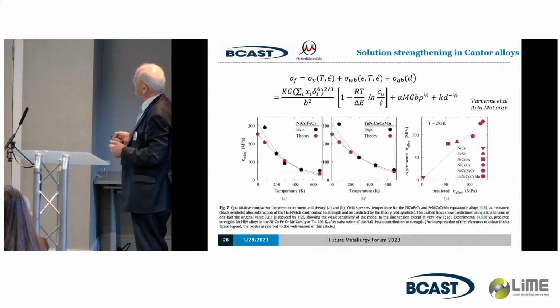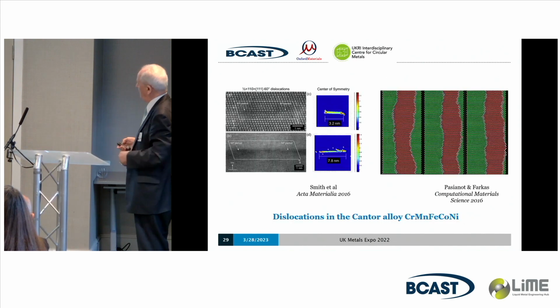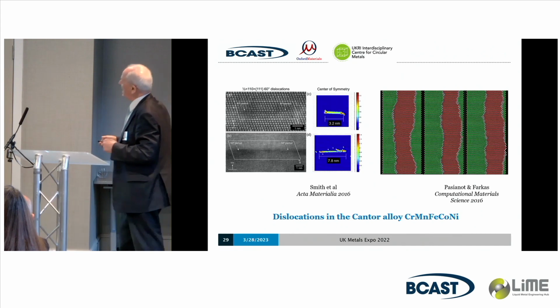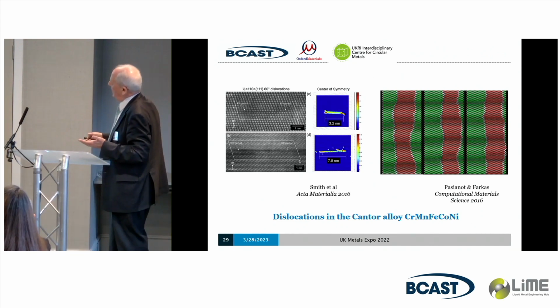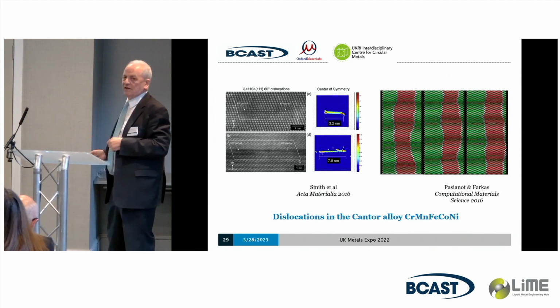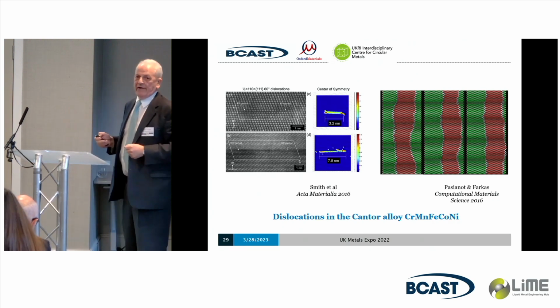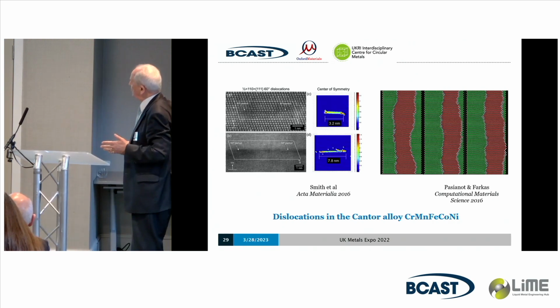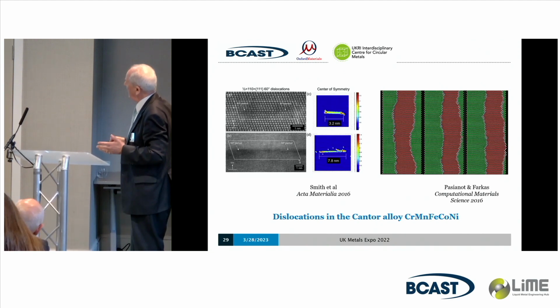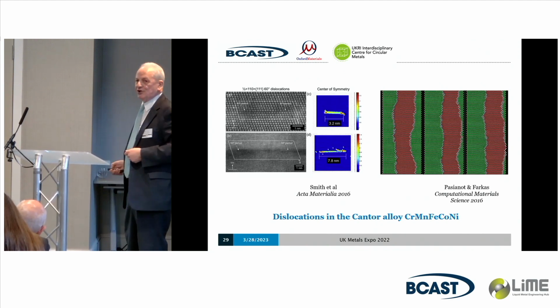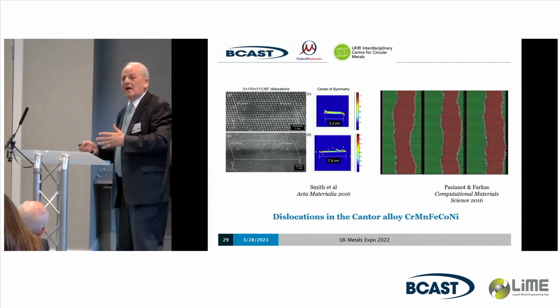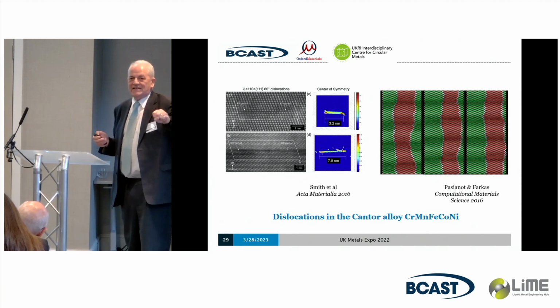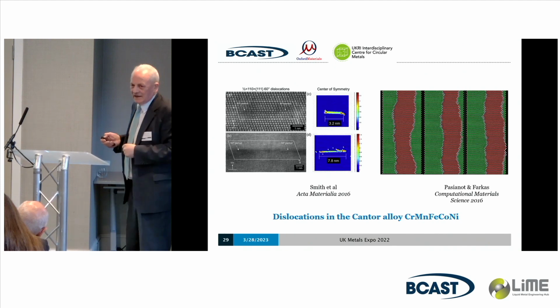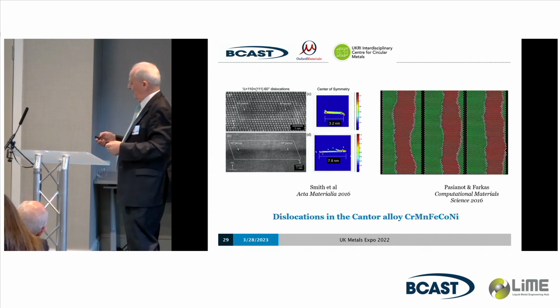So the theory of that is complicated, but it fits extremely well with experiments, and it's been done in a whole series of cases. Here are some pictures. The stacking fault energy is low, so you get a separation of partials here. But the separation of the partials varies as you go along the dislocation line because the structure is varying as you go along it. Here is some modeling to show the two partials, and as it's put under stress, it moves in this very jerky way. And it needs a high stress to move it past, as every atom is a center of strain and a center of restriction on the motion.